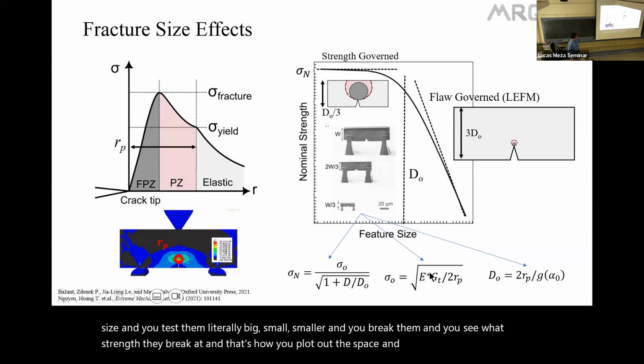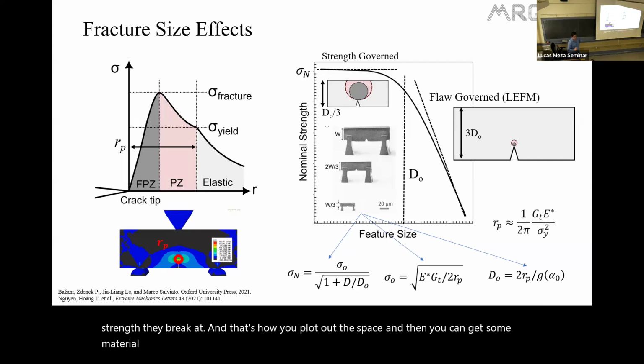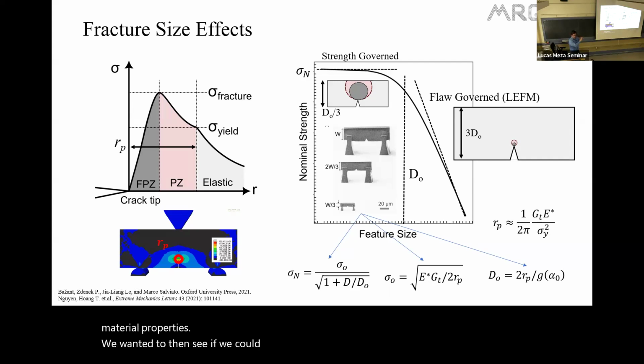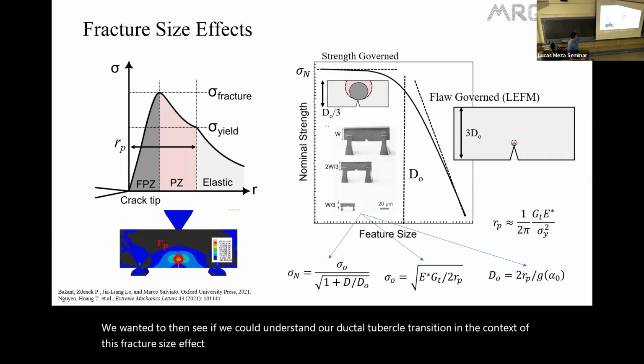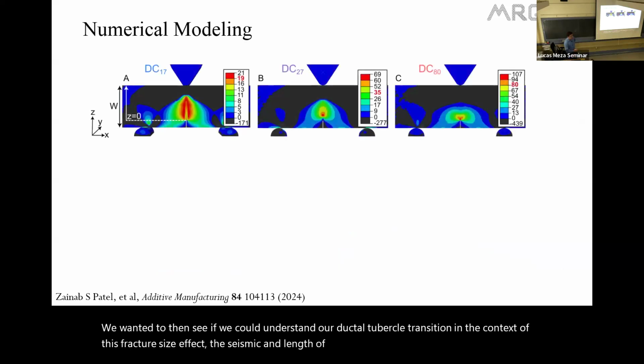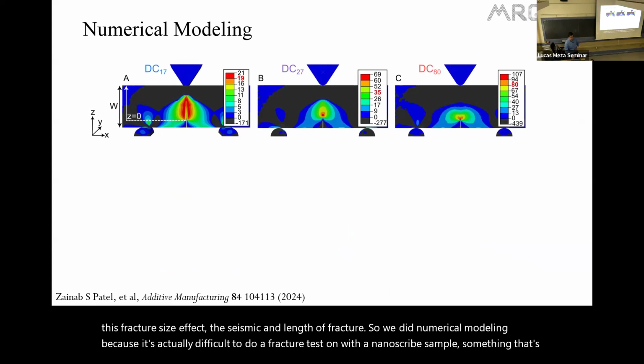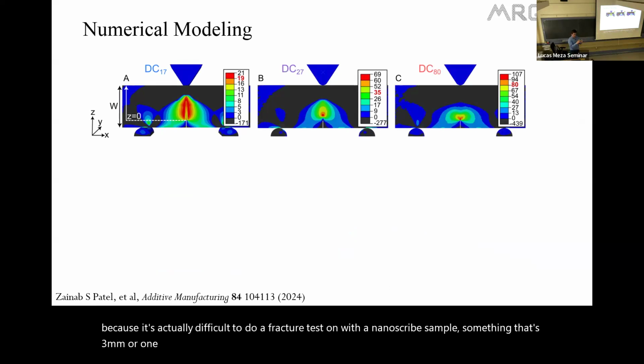And then you can get some material properties. We wanted to then see if we could understand our ductile to brittle transition in the context of this fracture size effect, the size affected length of fracture. So we did numerical modeling because it's actually difficult to do a fracture test with nanoscribe samples, something that's 3 millimeters or 1 micron. We're somewhat limited in how big or small our samples can be.